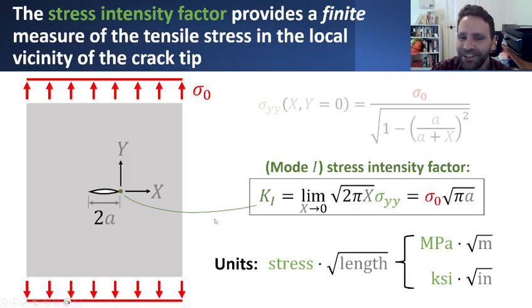It has some very unusual units. Because we're taking some stress times the square root of 2 pi times x, which has units of length, the resulting units of the stress intensity factor are stress times the square root of length. So things that look like megapascals times the square root of meters, or kips per square inch times the square root of inches. It's really a non-physical unit. And it doesn't really have any physical interpretation other than the fact that it came from exactly taking this limit, which gave us some kind of finite number in the limit as x went to zero. That's why it has these units. And again, it really doesn't have a good physical intuition behind it, so don't try to rationalize that so much.